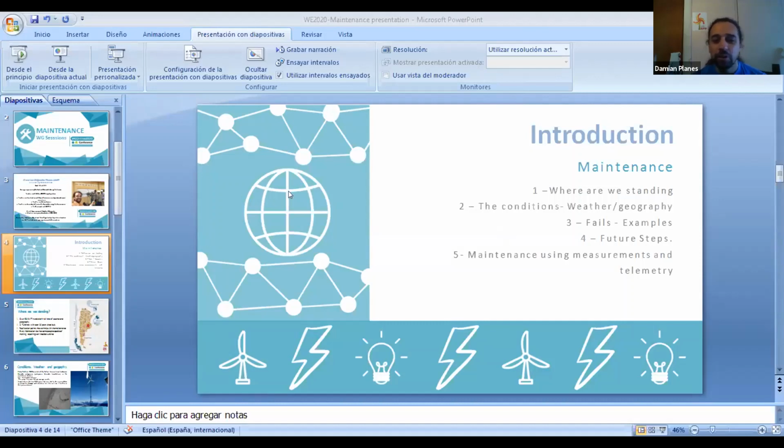You have my contact. I do the blade maintenance. If the blade is wooden, I usually make one or two repaintings of the blade. Normally, as preventive maintenance, we put on a varnish or a new paint coat, so we ensure that the wood is not in contact with the air. Doing that, we have propellers that worked for over 10 years.